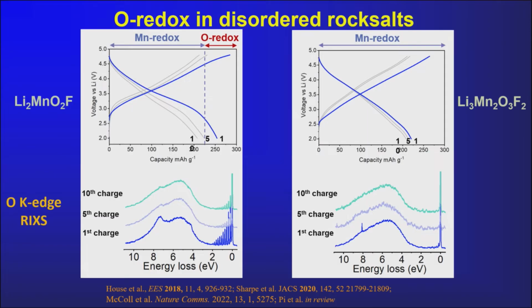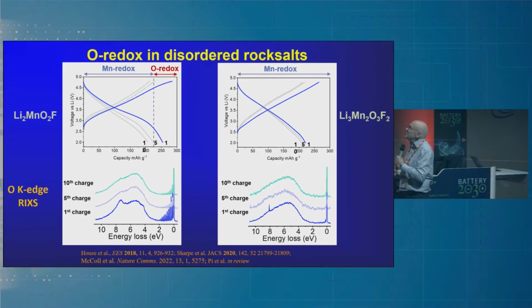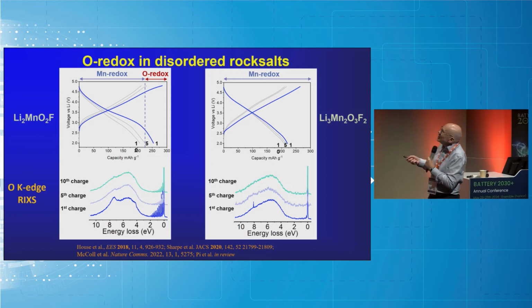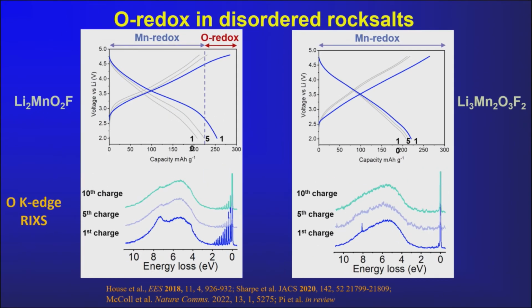Okay, very, very quickly, you can get oxygen redox in lots of other structures, not just layered compounds. Here's some disordered rock salts. This one here has oxygen redox capacity, and there are the classic vibrational peaks for molecular oxygen in the RIXS. This one, with a different composition, another disordered rock salt, all of that capacity in this case is manganese redox capacity, and there's no evidence of molecular oxygen. So you can get this in DRX, or so-called disordered rock salts, but you can also avoid it.